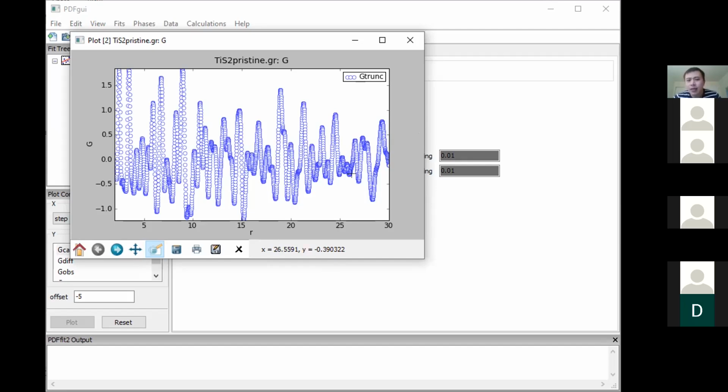But that's also the motivation why there are some neutron beam lines. They want to develop high resolution diffraction, so they can get a very high Q, but not at the cost of losing your peak resolution. So they can collect a very high Q, let's say to 30 Q range, but still your diffraction peaks are very well resolved.